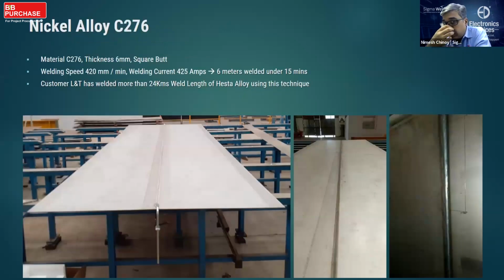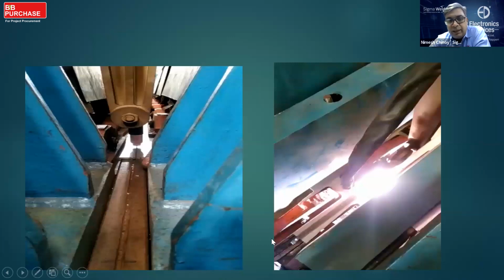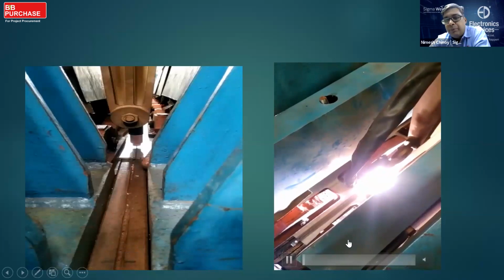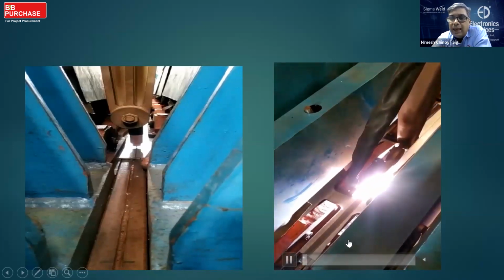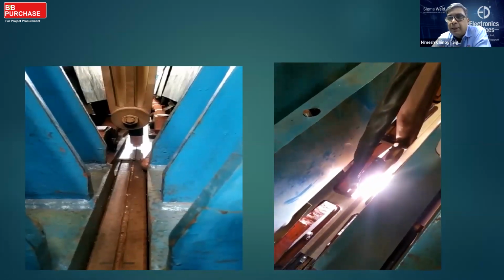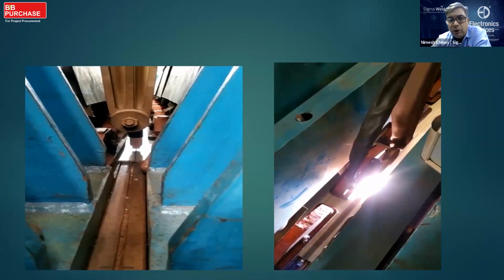There's another client who achieved a 6 millimeter thick Hastelloy plate C276, 6 meter long, in under 15 minutes. This is a plate before welding, after welding, and the root penetration. There is no distortion on the plate, thereby producing speeds of more than 420 millimeters a minute. This is one of the same plates that was welded, the actual fit up and welding procedure. This is being welded at the actual speed of 420 millimeters a minute. And you can see absolutely no problem.